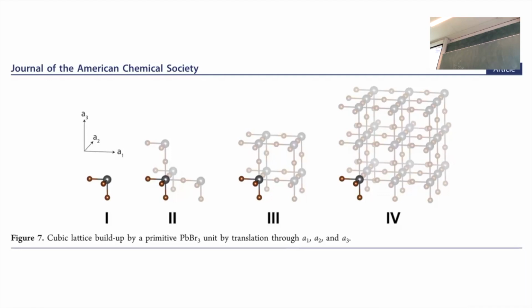If you look closely at this picture, then you see that at this side, and at this side, and at this side, there are all these octahedra. They are forming the end of the crystal. But on the other side, there's actually the lead ions on top. So these three sides of the crystal, as it is drawn here, have a different outside than the other ones. That's not what you want. You want to have intact octahedra. Otherwise, you have dangling bonds.